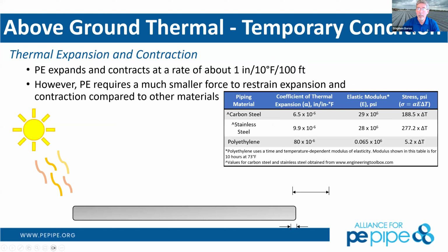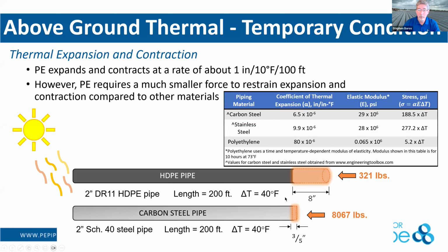Thermal expansion contraction. Polyethylene does have a higher thermal expansion coefficient. However, it's very easy to restrain because the force that it develops is very, very small. So with polyethylene pipe, let's say you've got a piece of 200 feet of pipe and the delta T of 40 degrees Fahrenheit, you may get, theoretically, as much as 8-inch expansion from that. Well, to restrain that, it's only going to take 320 pounds. Whereas if you had carbon steel pipe, yeah, it may only move 3/4 or 3/5 of an inch, but it's going to take 8,000 pounds to restrain that piece of carbon steel pipe if you don't want it to move off that flange adapter or that valve that you may have in place. So again, you need to take all that into account with polyethylene.